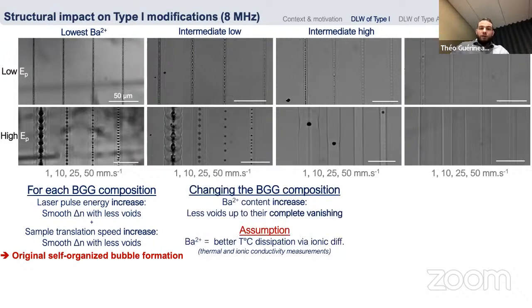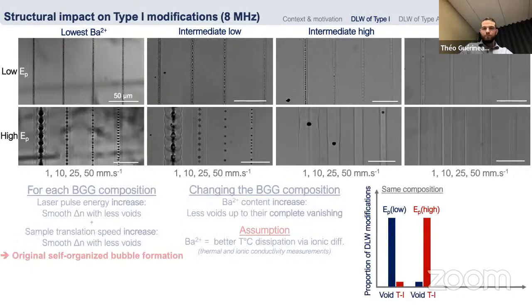When we change the BGG composition through the increase of barium content, we have less and less voids up to their complete vanishing. And so in this slide, our big assumption is based on the fact that the barium content, or the barium cations, help a lot to dissipate the heat accumulation via ionic diffusion. But we need to experiment that through thermal and ionic conductivity measurements.